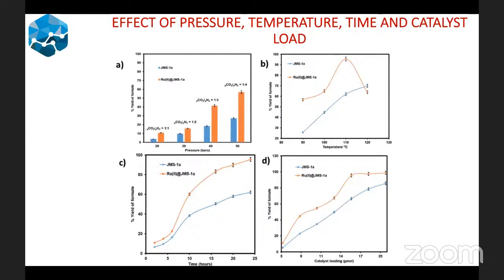And as you can see for the two systems, as you increase time, the amount of formate that was produced also increases. And of course, we also evaluated the load. Clearly you can see that an increase in the load also results in an increase in the amount of formate that is produced for the two systems, that is the functionalized and unfunctionalized MOF.